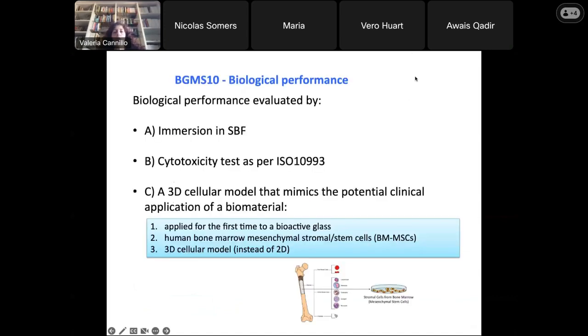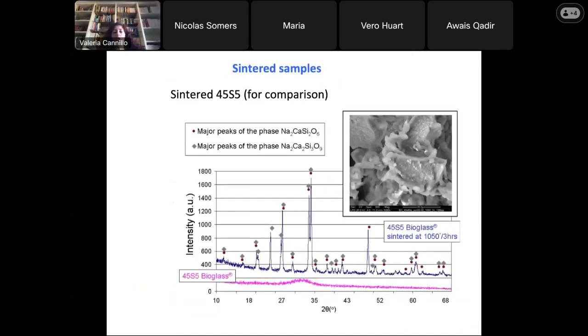Just for comparison, here you have a sintered 45S5. It was necessary to sinter it at 1050 degrees for 3 hours. And from the spectrum, you see that while the starting bioactive glass is completely amorphous, once you sinter it, there are many, many crystalline peaks.